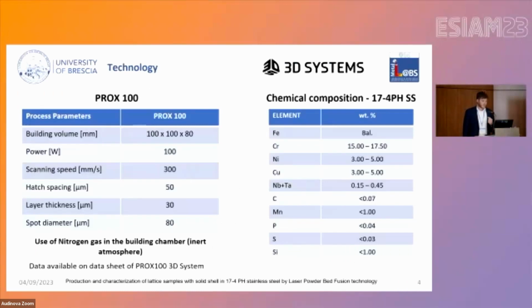We use the ProX 100 by 3D Systems, and we use the process parameters that you can see here in the first table. In particular, we set the power to 100 watts and a scanning speed of 300 millimeters per second. Another important thing is the building chamber that we inflate with nitrogen. This is really important for the inert atmosphere, not only for the oxidation, but also for the microstructure of the built component, because it's not the only gas that we can use with this kind of technology. The chemical composition of the powder is also reported here in the second table.